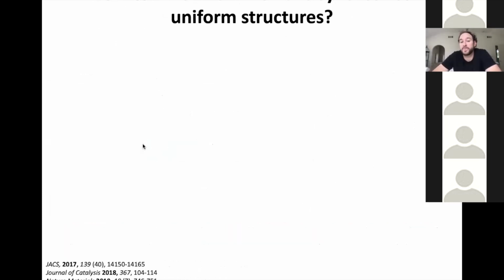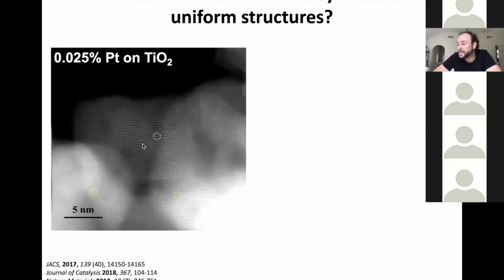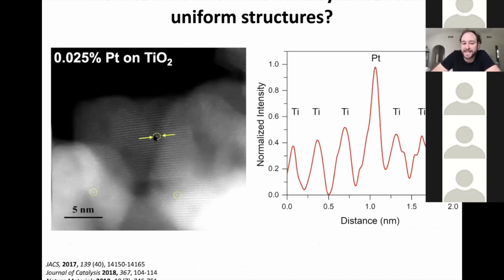So how do we know when we've synthesized a uniform structure? The first thing I always see is people wondering how you look at these TEM images and how you convince yourself that there's a single atom there. So what we do is we try to do line scans always, and we try to do line scans only when we've oriented our electron beam in the microscope along a particular zone axis of the support. The approach here is so that we can see diffraction beats, and if I line scan across here, this is the electron scattering intensity as I move across here.